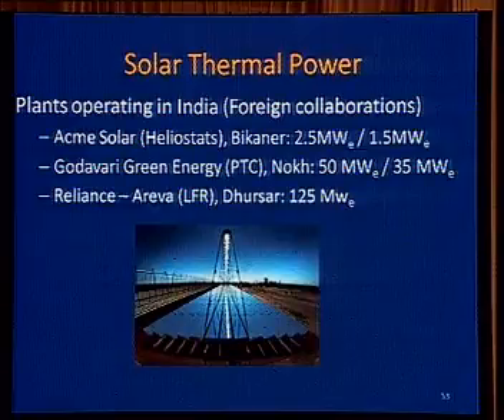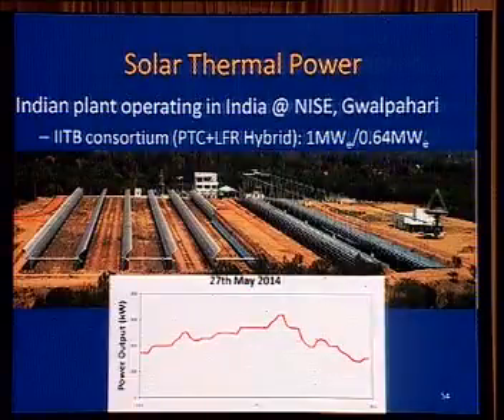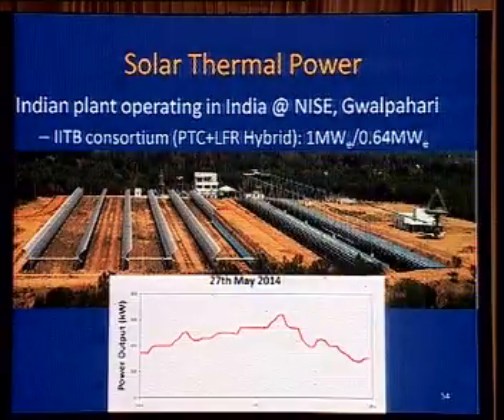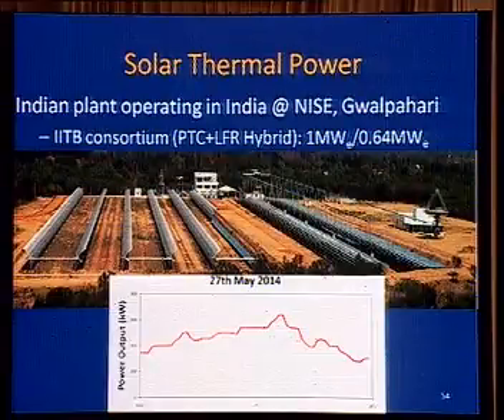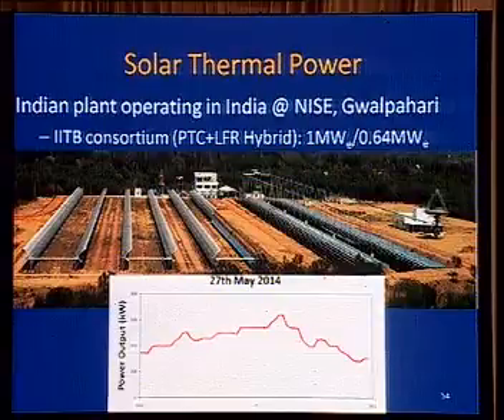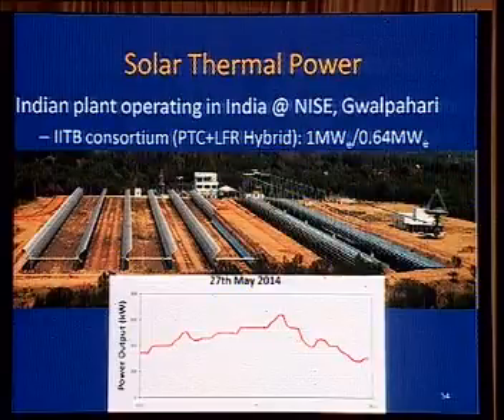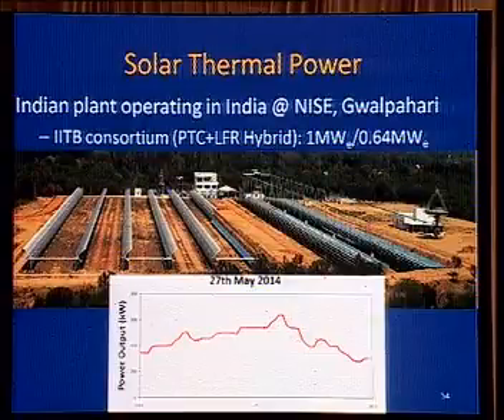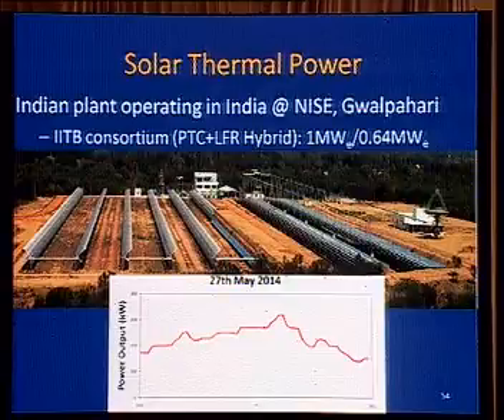So we have all three types of systems, and one of the systems that we at IIT have designed and installed at NISE, Gwalpahari is a combination of technologies. On the right you can see the LFR system, on the left you can see the parabolic trough system. LFR systems go to a lower temperature of 250 degrees Celsius, but they are more economic. So it generates steam by that, and by parabolic trough we heat oil to 400 degrees Celsius and superheat it, so that you can get better efficiency from the turbine. So this combination is unique. Nowhere in the world have people done this, but we are running a plant on this system. And there is a test center also. On the right you can see a small building, which is a test center. This is the data from when we actually generated power on 27th May 2014, and you can see that it went up to 600 kilowatt for some time, 2-3 hours.